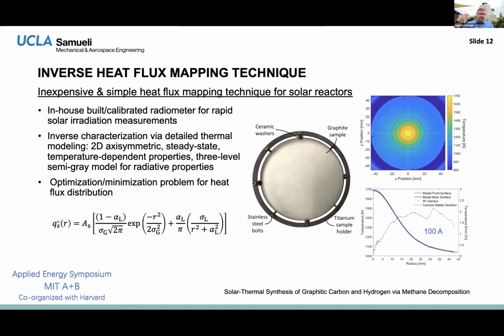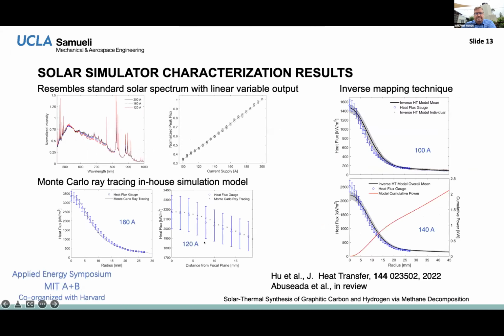a one-dimensional flow problem. When we actually flow methane and products through this, it's a very thin material, and so we are running many experiments at different temperatures all at once in a single run, having a temperature distribution like this. But for this case, what I'm talking about here is just to calibrate our light source. It ends up being best fit by a combined Gaussian-Lorentzian function that's shown on the bottom here. And so we've characterized this again spectrally.